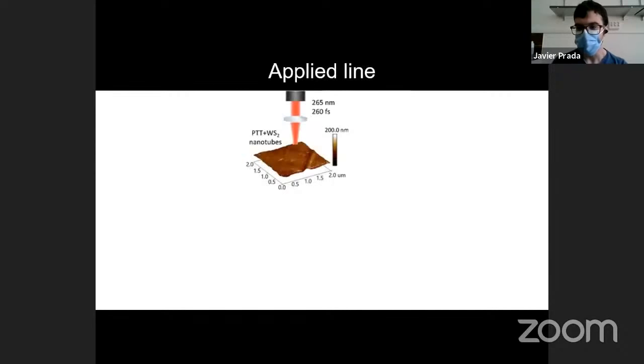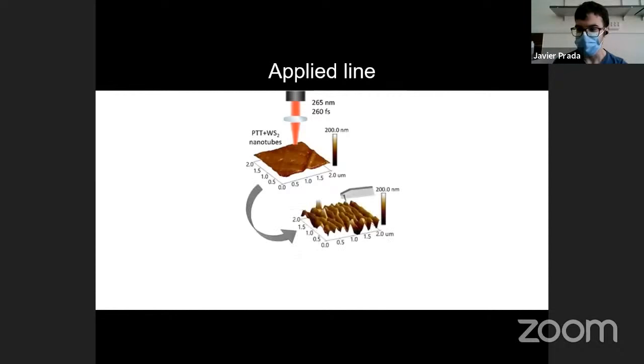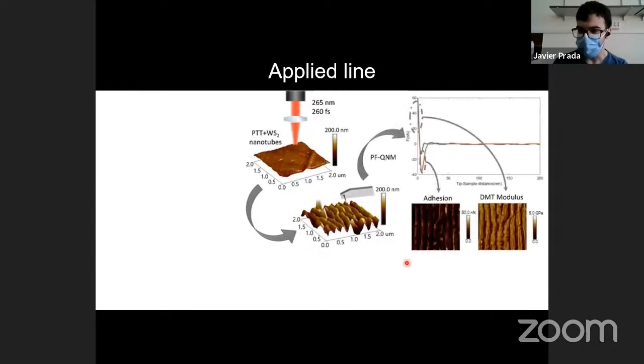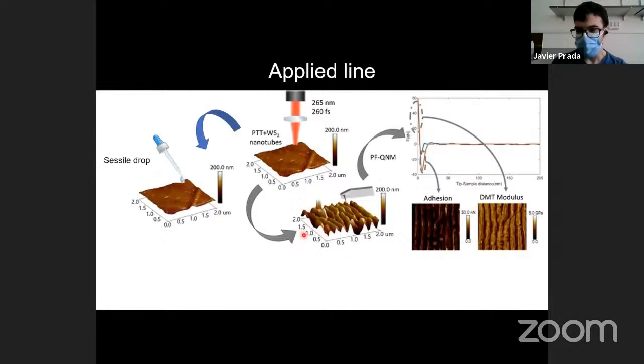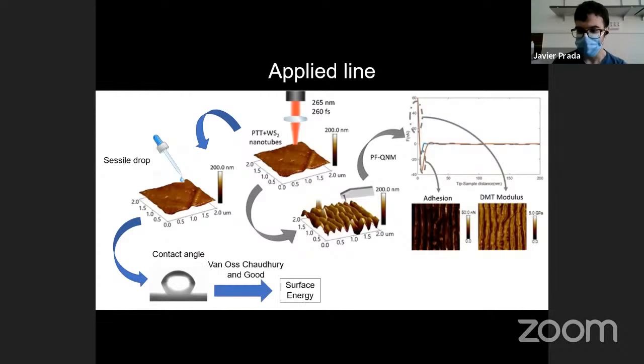In the applied line, we irradiated a polymer and a nanocomposite based on it with laser pulses and characterized the changes in their topography with atomic force microscopy and their nanomechanical properties with peak force quantitative nanomechanical mapping, which is a technique based on atomic force microscopy. And we used the sessile drop technique to measure the contact angles of different liquids before and after irradiation. From it, we obtained the wettability of the sample and the surface energy.